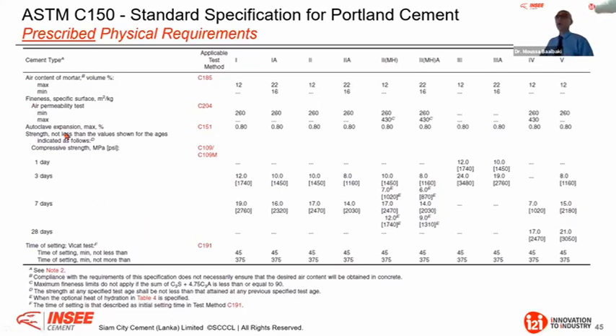After that we have autoclave, for soundness, where you also have a performance-based test at 0.8%, okay? Therefore, you should not exceed this value. Now, in terms of strengths, I will show you one slide when we compare ASTM to EN, because, again, it is very difficult to compare them, okay?